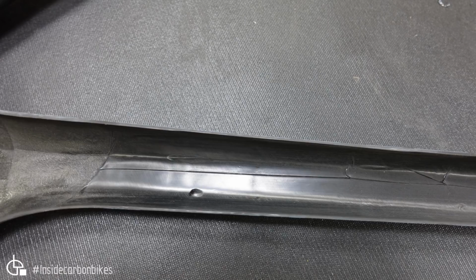And so here we get another look. You can see a nice view of that void there, and the other ones here. But what was of real concern when I scanned the bike, there was an area in this region here, and that all showed up as being areas of porosity, and I'll show you a bit more of that on the close-up a bit later on. But that's quite a concern, and it's right near the transition between the EPS type molding system and then where it just goes to a regular bag. So you've got the bag on this side of the line, and you can see the line there, and that's sort of where the issue is greatest. So that's a bit of a concern.